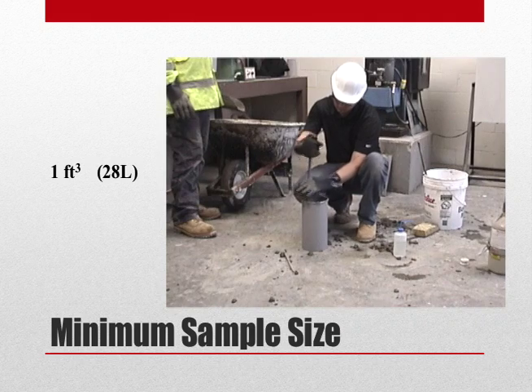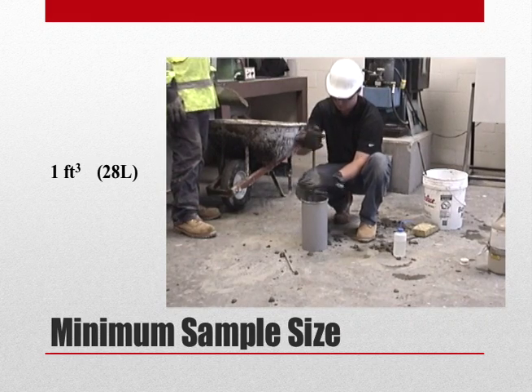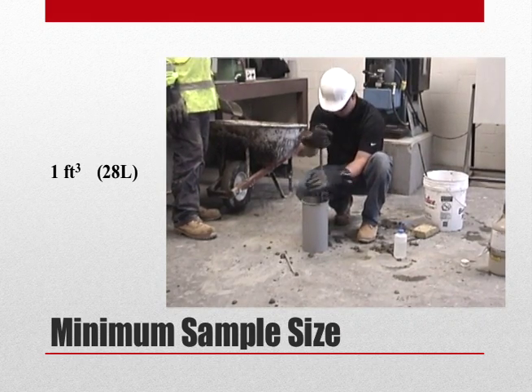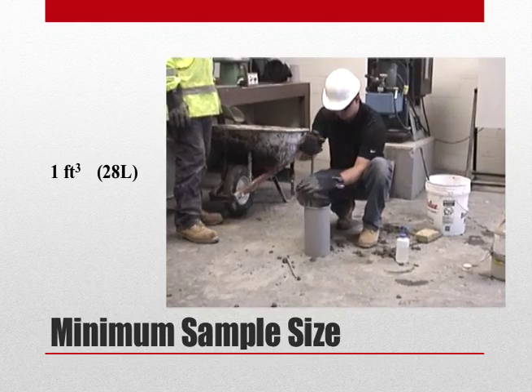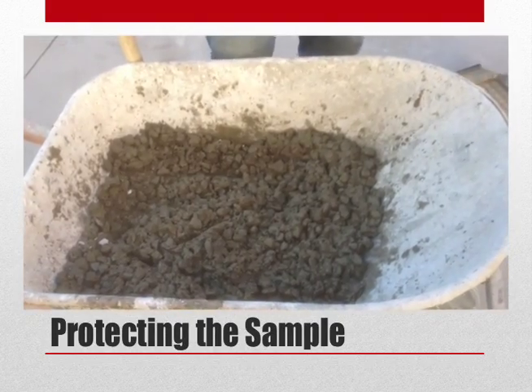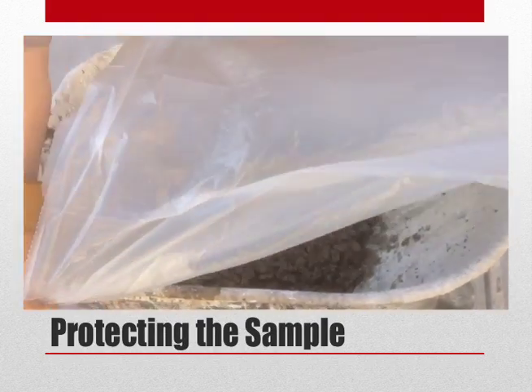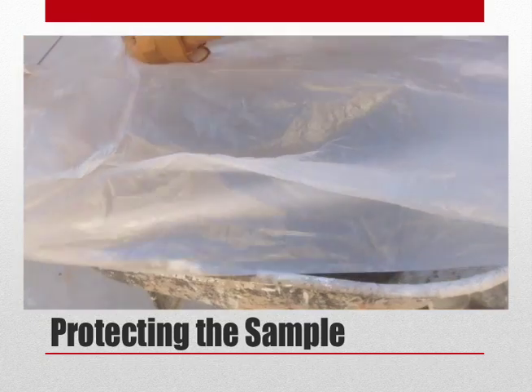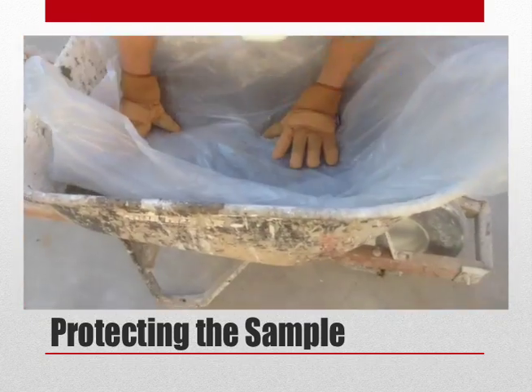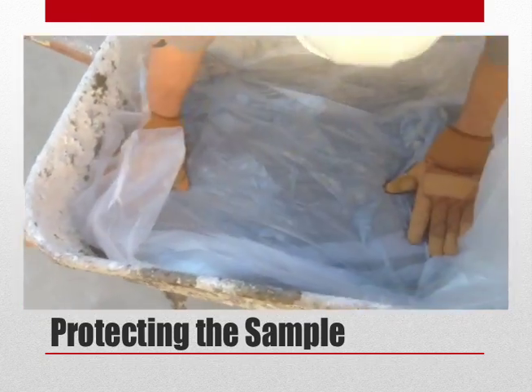When strength specimens are to be made, the minimum size sample obtained shall be one cubic foot. Also, as soon as we obtain our sample, we want to take steps to protect it from contamination and rapid evaporation.